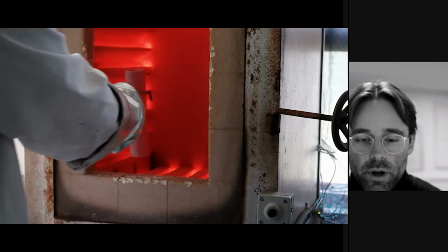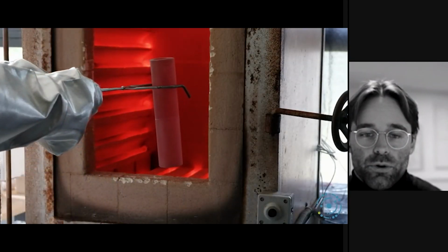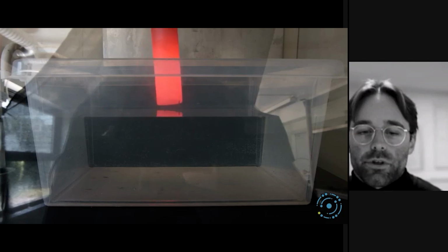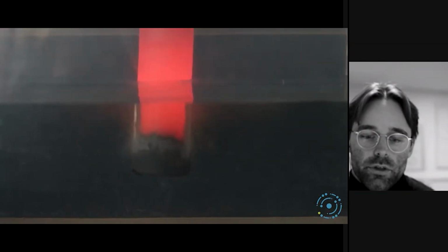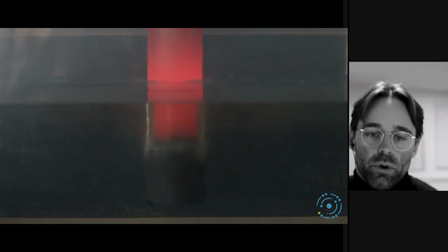Here I'm showing silicon carbide tubes at 900 degrees Celsius. We're getting tubes from different vendors and then stress testing them by dunking them into room temperature water, simulating a worst case accident in one of our cores if water spilled in past its containment into the insulation layer and directly onto the silicon carbide.